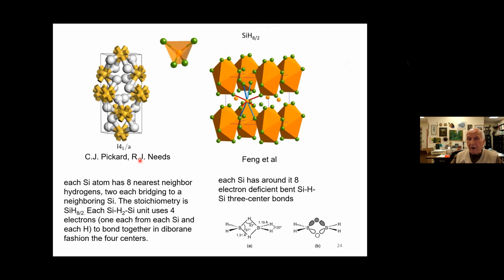At 100 gigapascals, we found a structure which is at right over here, where each silicon, one of these dodecahedra is stripped away. Each silicon has 8 hydrogens, which are shared with 8 other silicons. And so this is SiH8, and then each of them is shared with 2 silicons. So the stoichiometry is SiH4, but this is now a three-dimensional array. It's no longer a simple molecule that you can recognize. Pickard and Needs found a structure slightly lower in enthalpy that also has 8-coordinate silicon, but now each silicon shares with 4 surrounding silicons 2 hydrogens each. You can see this diborane-like unit over here.